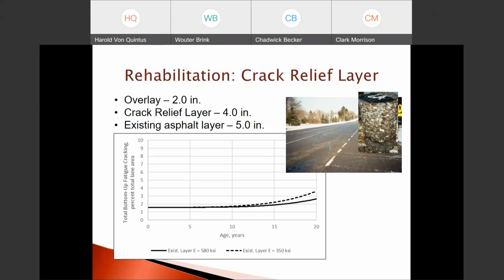in the asphalt 2-inch overlay over 20 years. And you can see almost none of the cracks, or less than 4% of fatigue cracks, are going to reflect. The solid black line is for the existing back calculated modulus of 580,000 PSI. And the short dashed line is the condition where we have 350,000 PSI back calculated elastic layer moduli for the existing asphalt layer. So the solid black line is a reasonable condition, has some damage. The short dash line would have a lot of damage in that existing layer. But this crack relief layer under this condition basically delayed those cracks from reflecting through the surface for both conditions over 20 years.